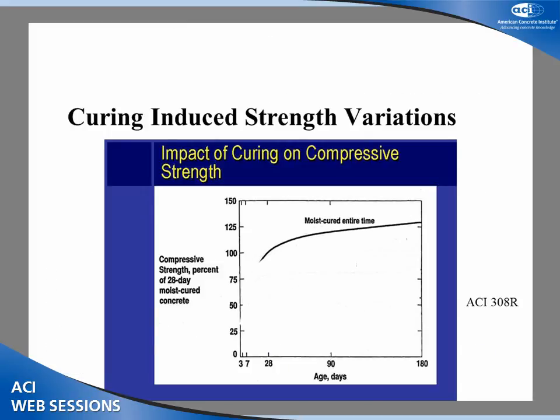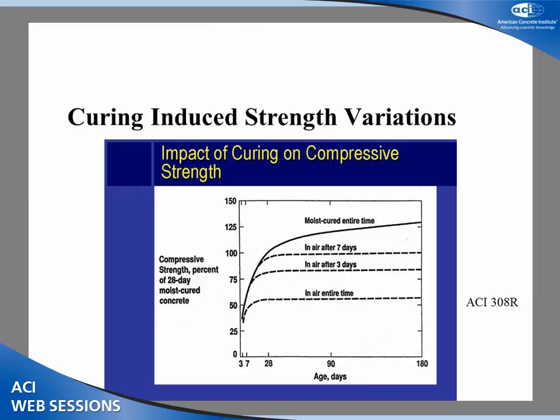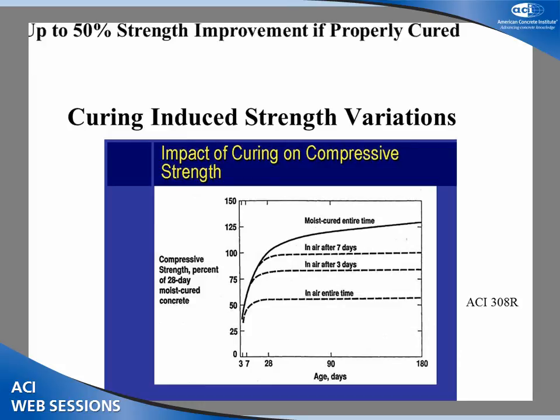Curing. If I moist cure the entire time, I get 125% of what I get if I only cure for 7 days. If I only cure for 3 days, I'm down about 25%. And if I air cure the entire time, about 50%. This is right out of 308.